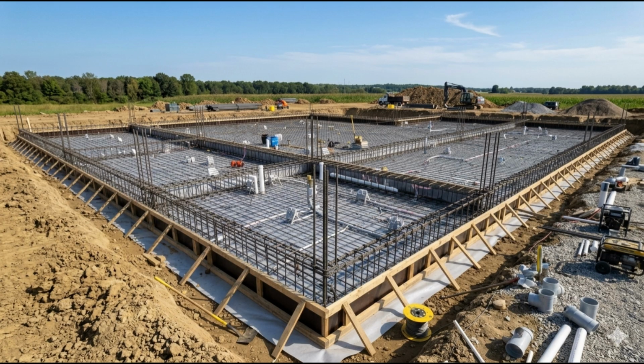The joints were to be sealed not less than 4 weeks after the pour, to allow the concrete to complete the majority of its drying shrinkage before the sealant was applied. Applying sealant too early meant that subsequent concrete movement could overstress the sealant and cause premature failure.